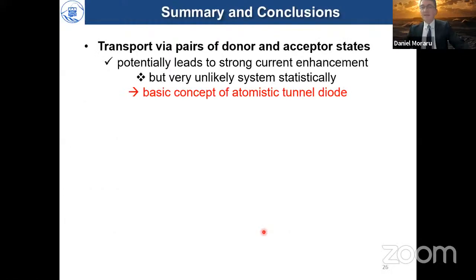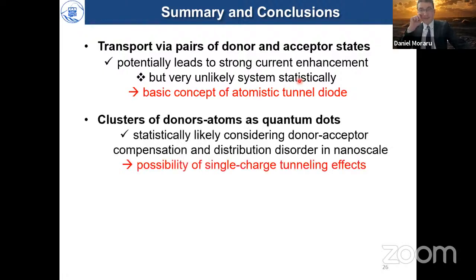So let me very briefly show you the summary. We report here transport through pairs of donors and acceptors. It can give strong current enhancement, but unfortunately it's difficult to control. Nevertheless, it allows us to think of a basic concept of atomistic tunnel diodes. A second result reported the clusters of donor atoms working as quantum dots. This is statistically more likely, and we can understand it by donor-acceptor compensation concept, and also by considering the disorder in nanoscale. And that gives us the possibility of single charge tunneling effects, another fundamental effect.